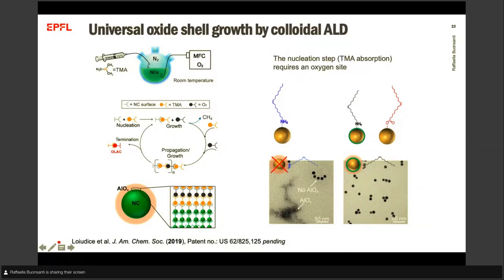And what we notice is that the ligands can also act as anchoring, as nucleation sites for the alumina layer. Basically, we do need an oxygen site, and this oxygen site can be on the surface of the nanocrystals if they are slightly oxidized, but the ligands themselves can also act as nucleation sites. And I now have a student who is continuing some NMR studies to better understand the role of the ligands in this colloidal ALD.